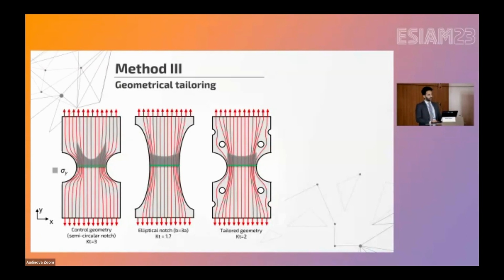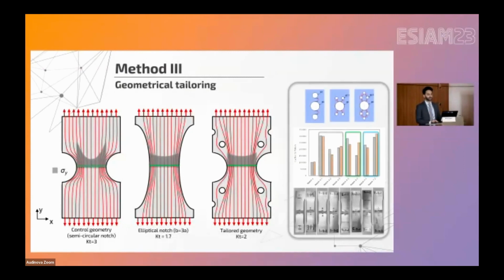So in the first part of the idea, we thought, okay, some odd idea. You have a notched component, you want to improve its performance, you add more notches to it. It works, it redirects the stress flow in the component and would result in a lower stress concentration factor. We did some preliminary work on this in different arrangements of this added notch, and the results were relatively promising. We could see that the fatigue life under that specific load was increased by a factor of 2 to 3. But let's be honest, it's not a clean way. It's not a designer's way to drill some holes. It doesn't seem practical. So we looked for a more controlled way.